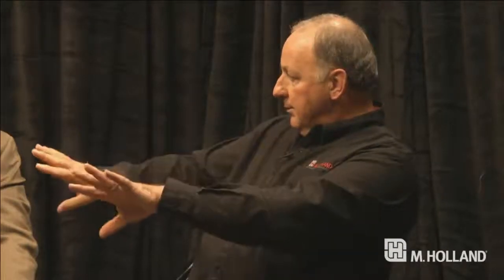And we put in polypropylene, because the dunnage bags are used in trucks and trailers between the pallets, and they inflate these bladders to snug up the pallet so there's no shifting during transport. They have to sonic weld a spout onto the plastic, and that does better with polypropylene than it does with polyethylene. So we were putting polypropylene in the core layer. Now, I've run a lot of polypropylene film, and 19 out of 20 times we lose the bubble, because polypropylene runs at a much higher heat setting than the polyethylene does. And to get everything just right,